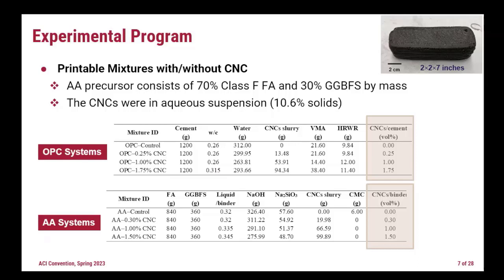At the bottom, you see the alkali activated system, again, control and different CNC proportions. In case of the alkali activated binder, we use a mix of fly ash, class F fly ash, and slag. So 70% fly ash and 30% slag. Again, I'm going to discuss how we come up with that number. The CNC were in aqueous suspension, around 11% solids. And for the activator, we use a combination of sodium hydroxide and sodium silicate.